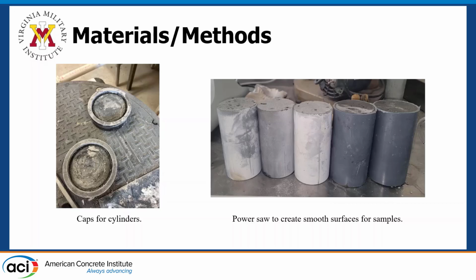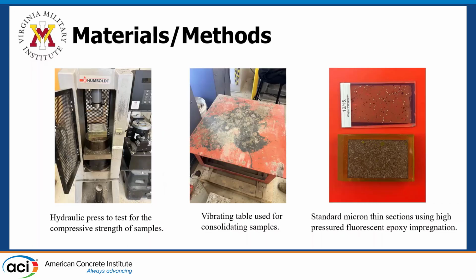These are the caps for 4x8 cylinders, and they actually have their own complications when using them with 3x6s, as you can imagine. Then we used a power saw to cut the surfaces of the samples, because when we originally cast them, they don't consolidate very well. A smooth surface is hard to achieve, so we had to cut off about 3/16 of an inch in order to facilitate proper breakage. We used a hydraulic press to test the compressive strength of the concrete. We used a vibrating table for consolidating each sample, and we used a standard micron thin section using high-pressured fluorescent epoxy impregnation. We would put those under a polarizing light microscope and the SEM.